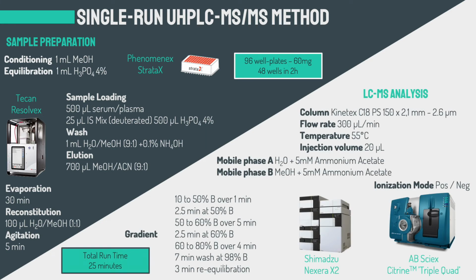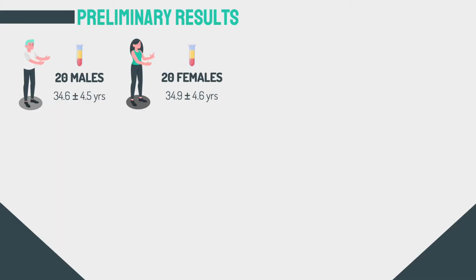For the instrumental analysis, we adopted the chromatographic condition displayed before, with a flow rate of 300 microliters per minute, keeping the column at 55 degrees and injecting 20 microliters of the sample. MS analysis was performed in polarity switching mode, and for each steroid, 2 MS transitions were selected and optimized. Thanks to the developed method, we are able to quantify the 30 target steroids in a single run analysis of 25 minutes. The method was then used to perform a preliminary study analyzing real plasma samples collected at the blood bank of the Turin University Hospital.